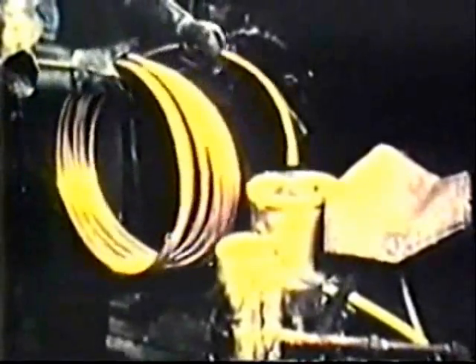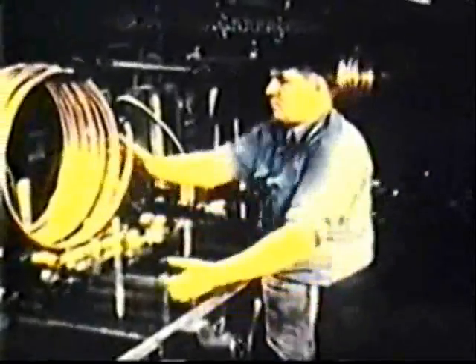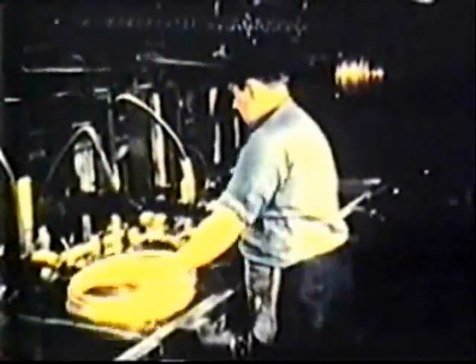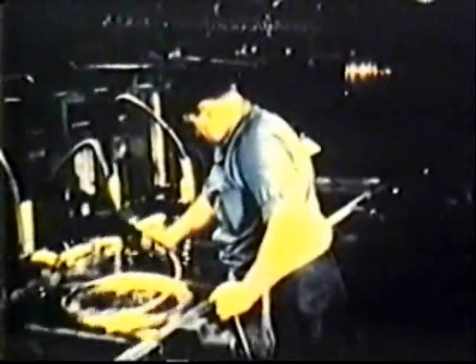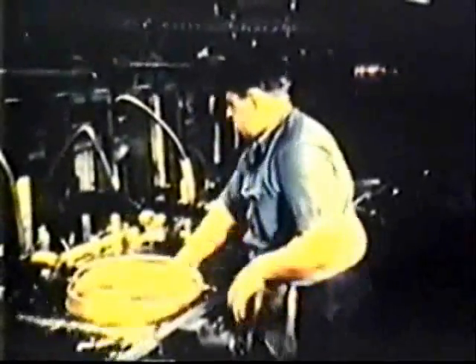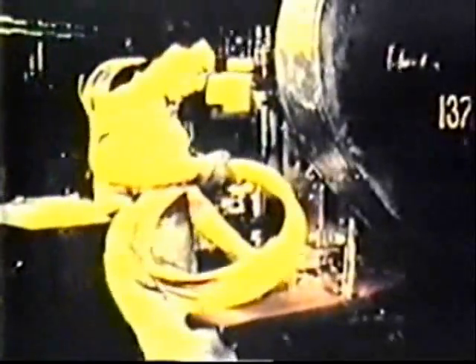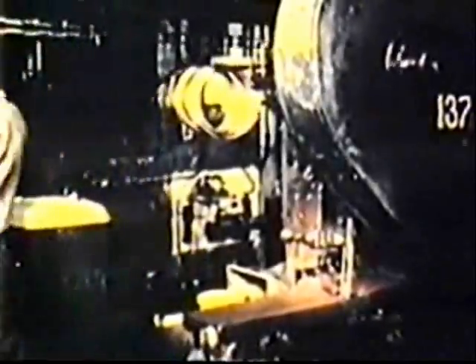All refrigeration tubing is pressure tested underwater. To permit this test, one end of the tube is crimped and dipped into a flux and molten solder. The open end of the tube is placed in a testing nozzle. The coil is submerged, and an air pressure of 250 pounds is applied. If the coil passes this test, the other end is then closed to prevent the introduction of dirt or moisture and to ensure a clean, bright tube for the customer. The coil is placed on a conveyor and given a final surface inspection before shipment.